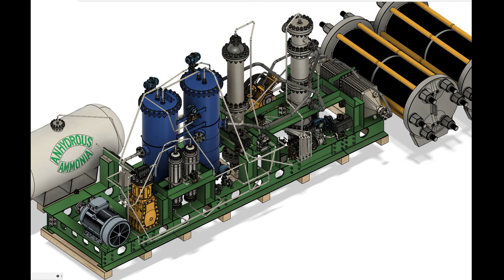Nitriding is a very gradual process, and the ensuing evidence of nitriding often occurs much later in the plant's life cycle. Nitriding is classified as a high-temperature corrosion process, taking place at temperatures greater than 370 degrees Celsius. Nitriding is considered an issue since ammonia synthesis operating temperatures almost always exceed this threshold.